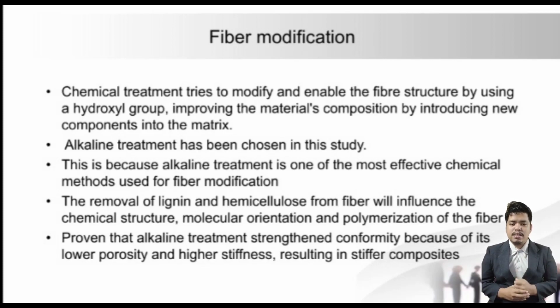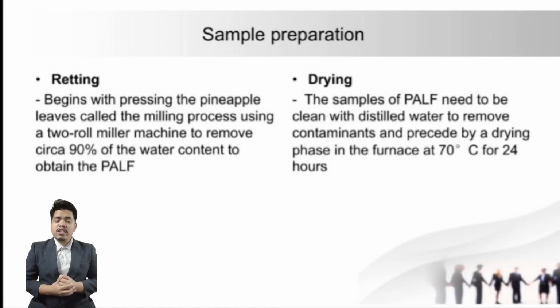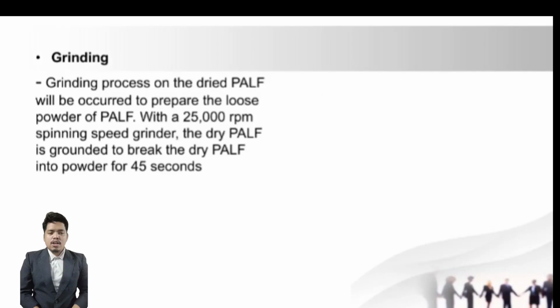Okay, so there are three steps required for the sample preparation, which are retting, drying and grinding. Okay, so first, retting begins with the pressing of the pineapple leaf fiber, called the milling process, to remove the water. And for the drying, the sample of PALF needs to be cleaned with distilled water to remove the contaminants, and it will be placed in the oven for 24 hours at 70 degrees Celsius. Okay, so for the grinding, the process on the dried PALF will be carried out to prepare the loose powder of PALF with a 25,000 RPM spinning speed grinder. The dry PALF is ground to break it into powder for 45 seconds.